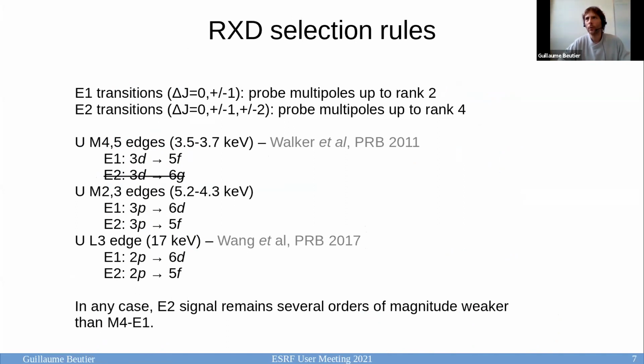So initially people were looking at the M4 and M5 edges of uranium, but unfortunately in this case you look essentially at dipole transitions, and in this case you can probe multipoles up to rank 2 only, and the quadrupole transitions are very weak in this case, because they would probe a 6g state. So to have a chance to probe multipoles of rank up to 4, you need to go to quadrupolar electronic transitions, and they are sizable, let's say, although weak, at the uranium M2 or L3 edge or uranium L2 L3 edge. And so this has actually been attempted and published in this paper, but at the time when we were going to do the experiment, this was not published yet. So that's why we had the same idea actually.